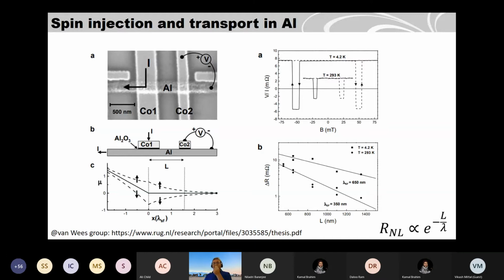So here you see the measurements at room temperature or also at low temperature. The switching field is different because this is the in-plane magnetic field, which changes the magnetization of this cobalt 1 and cobalt 2. So when both switch, you get to this parallel state here. And when one of them is anti-parallel, you go to this state. So you see the change in the resistance or the voltage when you try to detect the spins. This is called spin valve measurements.